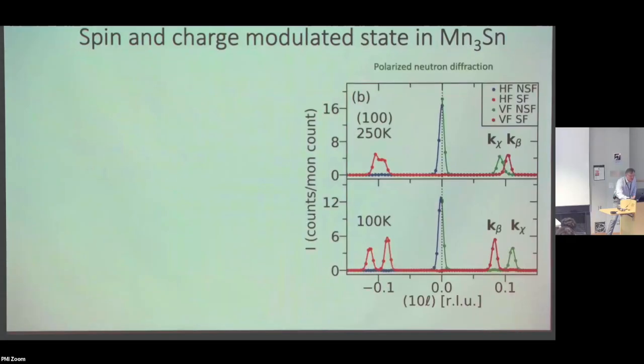So this was just a total surprise actually, which was we used polarized neutrons to resolve the incommensurate peaks that had been observed. Here I'm showing you data at 2 different temperatures, 250 and then 100 Kelvin, all in the incommensurate state. This had previously been just one peak, but we hadn't really noticed there were 2 peaks. There was a little bit of something, but when we used polarized neutrons, they're totally split out from each other. Furthermore, you'll see that the red one is higher Q and the low one is green, and then they switched at lower temperatures. So these peaks are actually moving about and crossing each other.